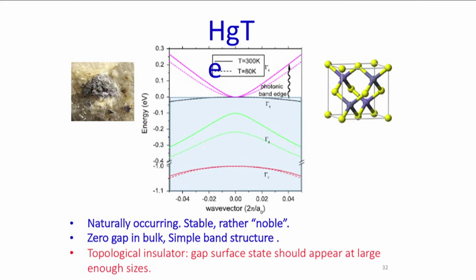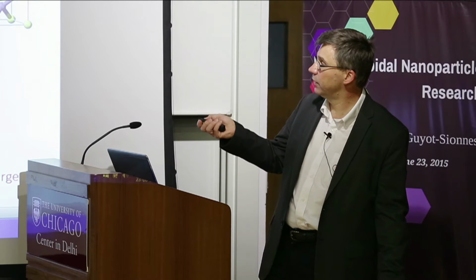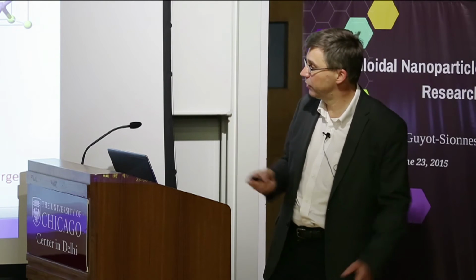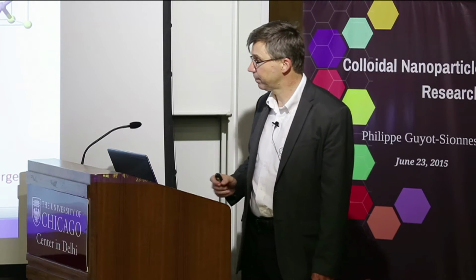Mercury telluride has a very simple band structure, a heavy hole band and an electron band here, the conduction band. So all you need to do is, in the quantum dots, you control the wavelength. The wavelength is inversely proportional to that wave vector here. And so the size of the particle defines the wavelength, which then defines the energy. A smaller particle would start here, a larger particle would start here, et cetera. And you can see that the energy gets smaller and smaller for larger and larger particles.